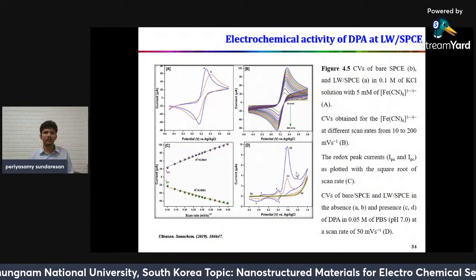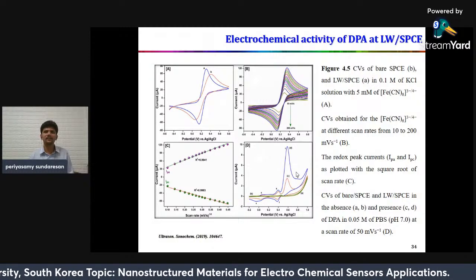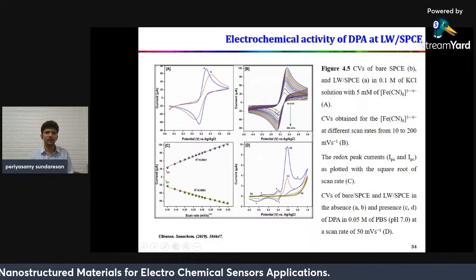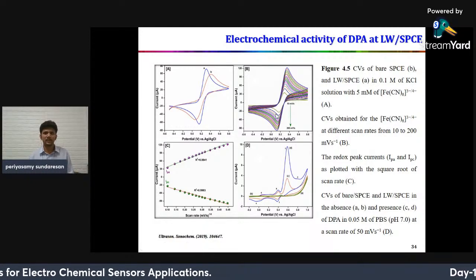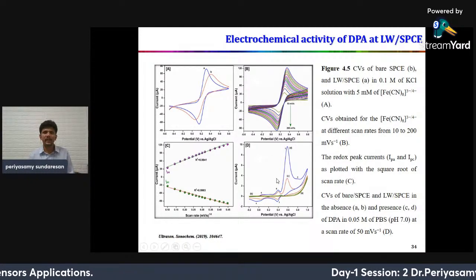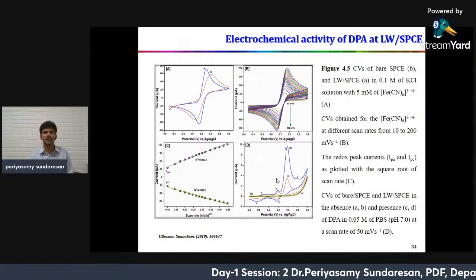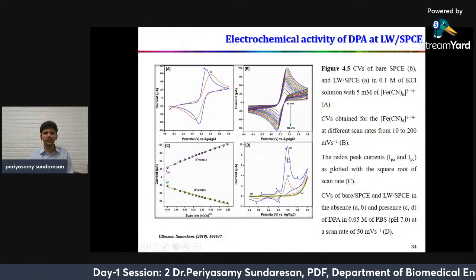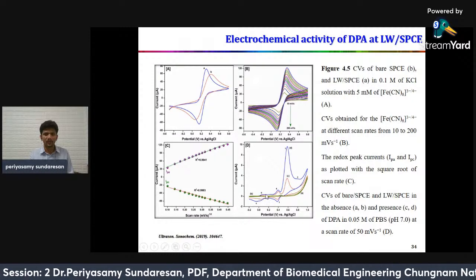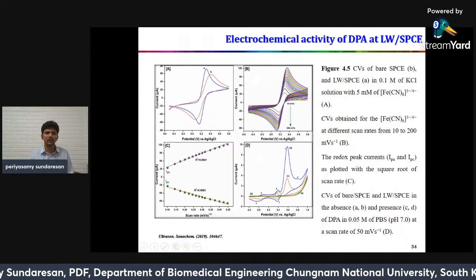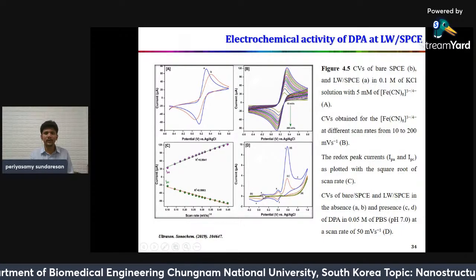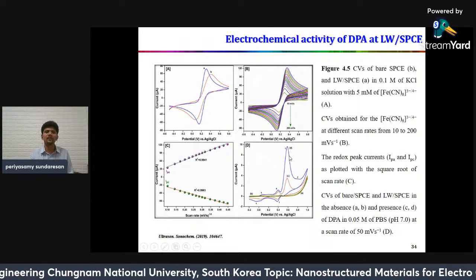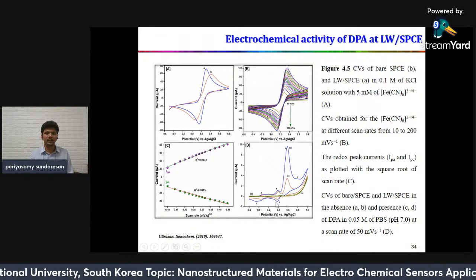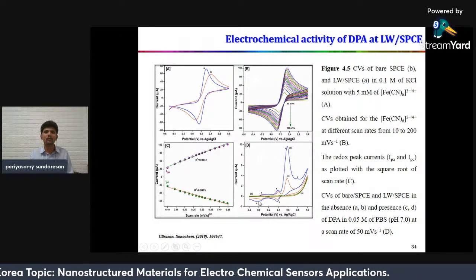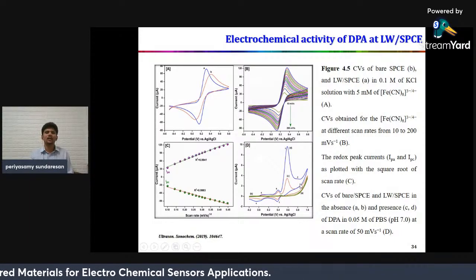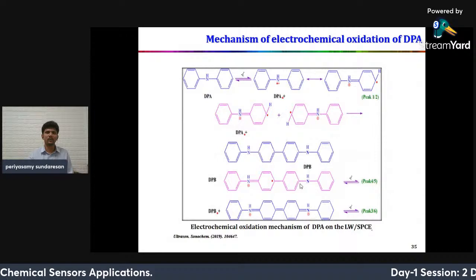This is the electrochemical study of the prepared catalyst. The ferricyanide system confirms the active surface area of the lanthanum tungstate compound. This is a cyclic voltammetry study of the lanthanum tungstate nanoparticles for the diphenylamine compound. Here I get 5 different peaks. The first three, at 0.2, 0.4 and 0.6, are oxidation peaks, and the remaining two are reduction peaks. The mechanism is shown here.